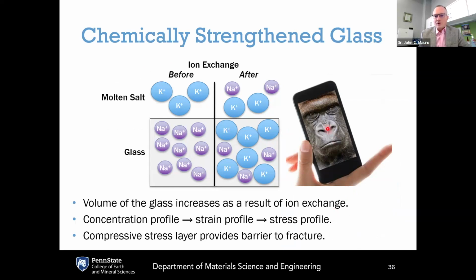The way that Gorilla Glass works is that the glass is designed to have a large amount of sodium in it. And then the glass, as formed, gets submerged in a molten salt bath, where that salt bath has a larger alkali ion. It's usually potassium nitrate. And this is done at temperatures of about 400 degrees C. So the glass has a lot of sodium in it. The salt bath has a lot of potassium. It's submerged in the salt bath for about 8 hours.